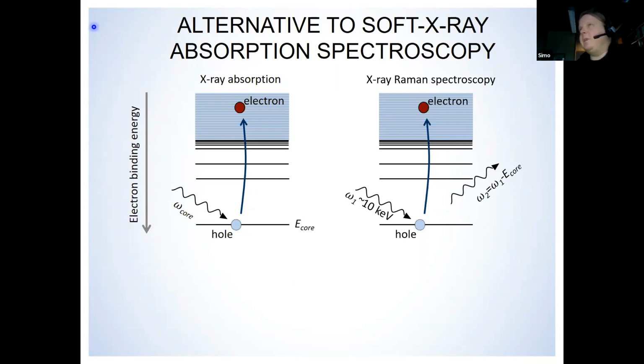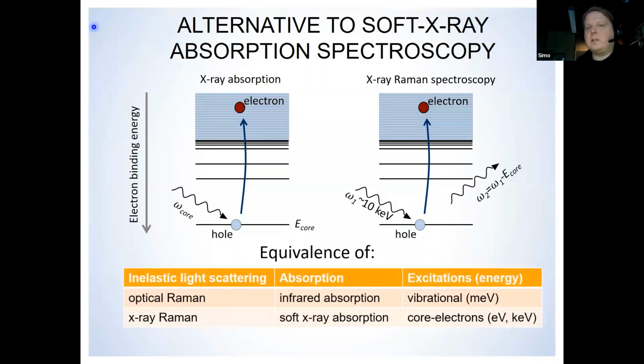So a typical IXS inelastic scattering beamline could use 10 keV photons to study processes in the electron-volt, 100 electron-volt, maybe keV range. One detects the outgoing photon with a diminished energy, and then deduces the spectrum of these excitations. From the electron system's point of view, the excitation is exactly the same in both XAS on the left and X-ray Raman on the right. The name Raman comes as an analog from optical Raman spectroscopy, which produces vibrational, milli-electron-volt range excitations, but X-ray Raman is then equivalent to soft X-ray absorption, creating core electron excitations. And this was dealt with very nicely yesterday by Jerry.